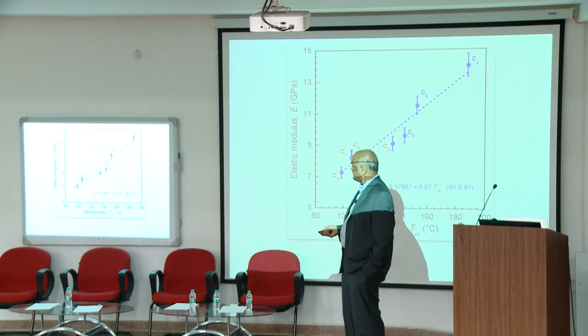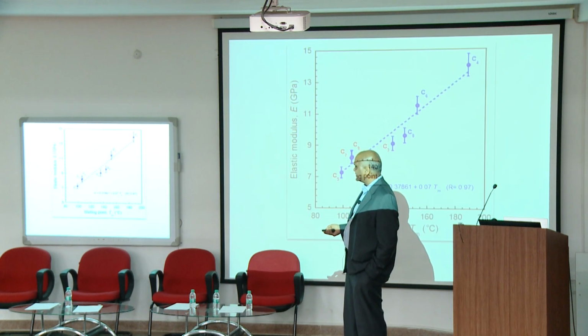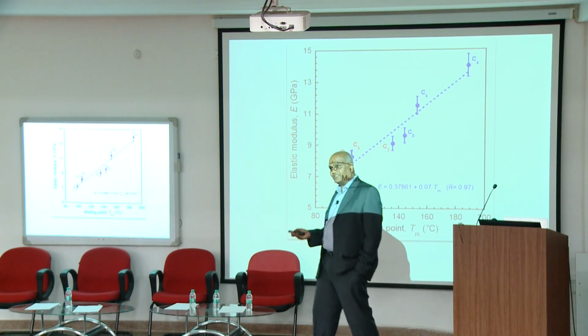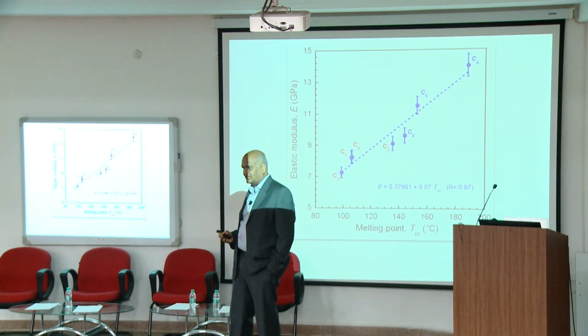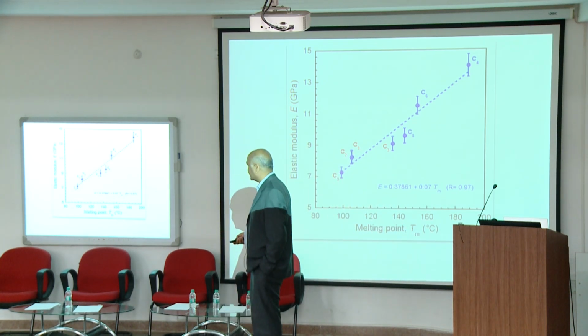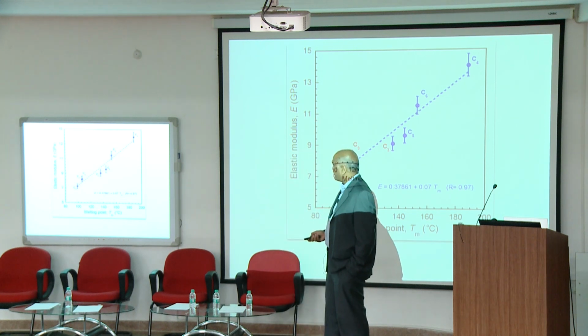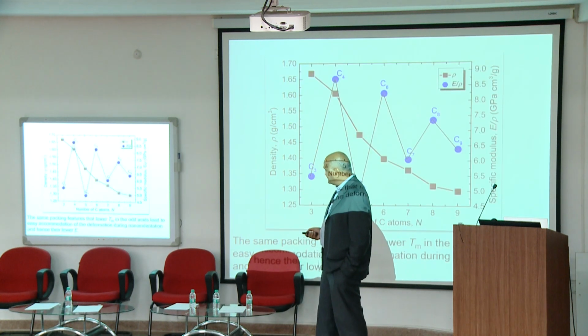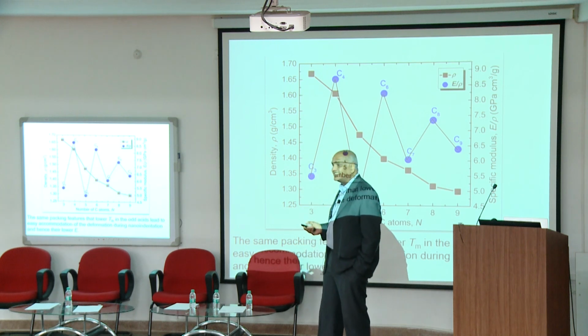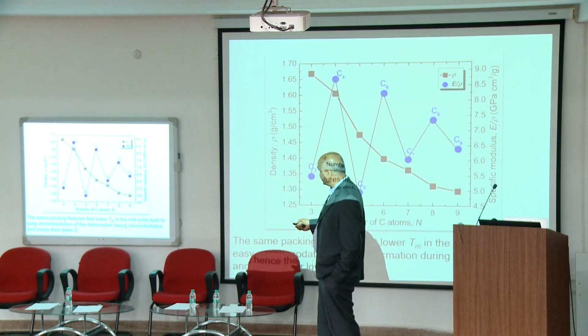And in fact, if I plot elastic modulus versus melting point, it's even better than what you see in metal, the correlation between these two properties. Okay, so, and it is not because of the density variations. There is a density variation like this, there is no odd-even effect.